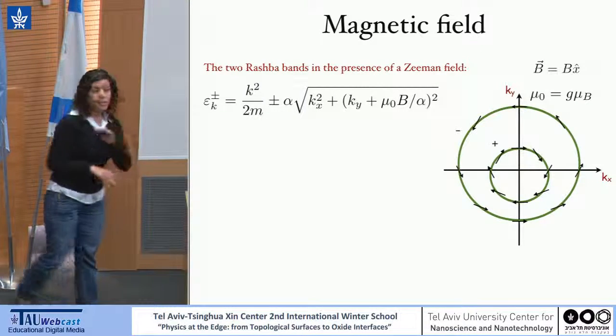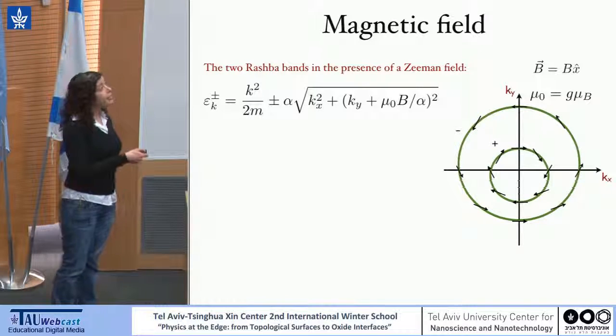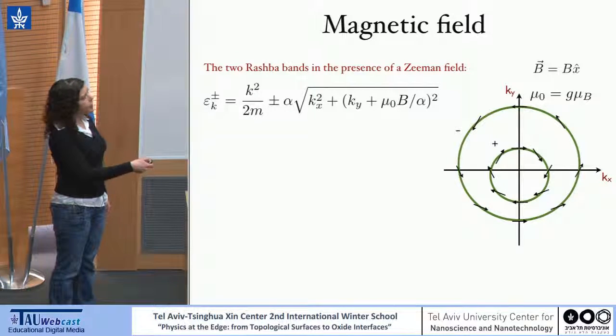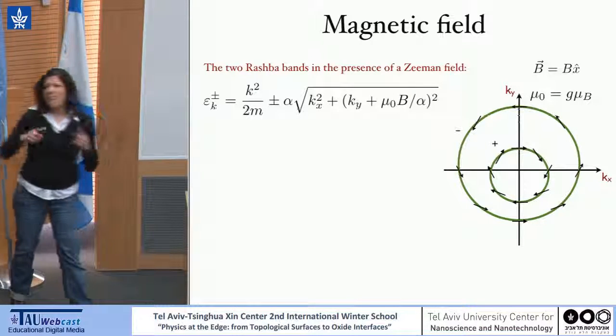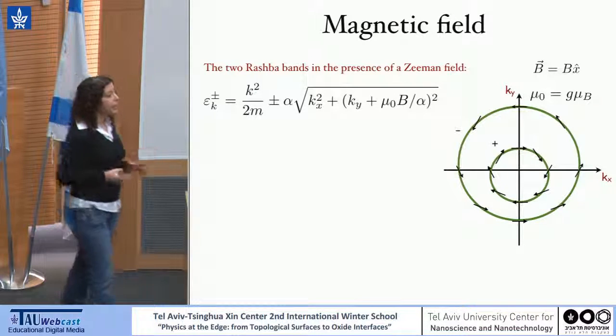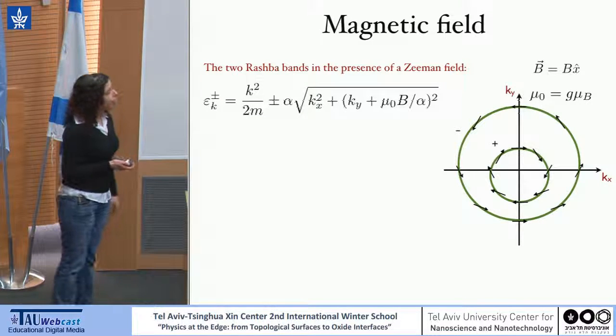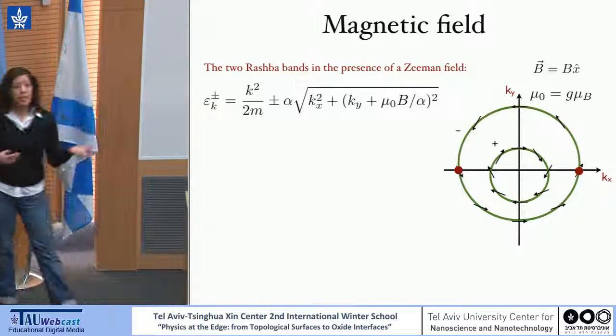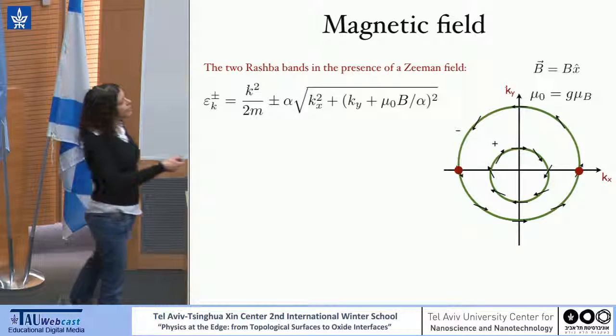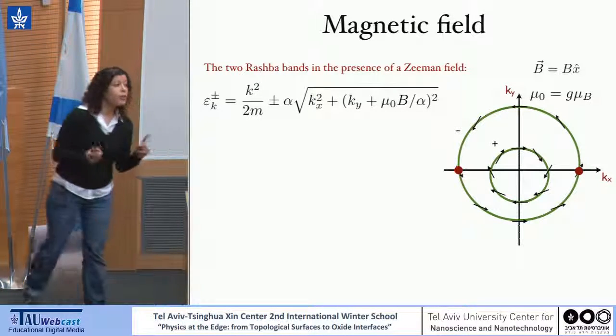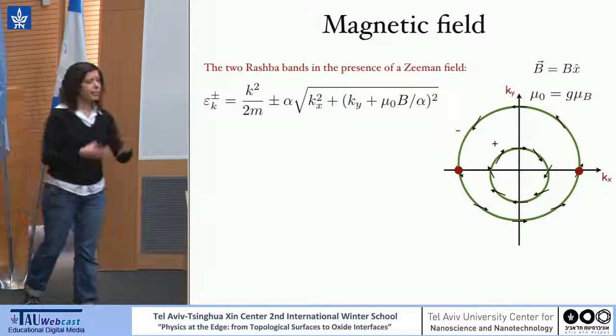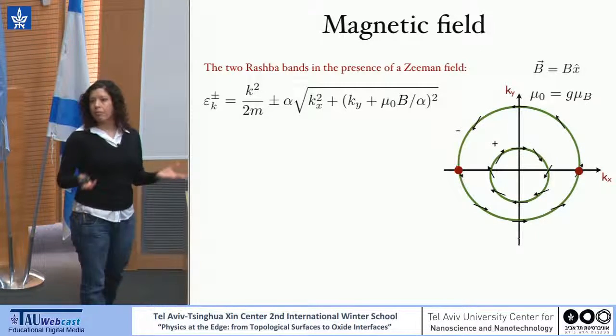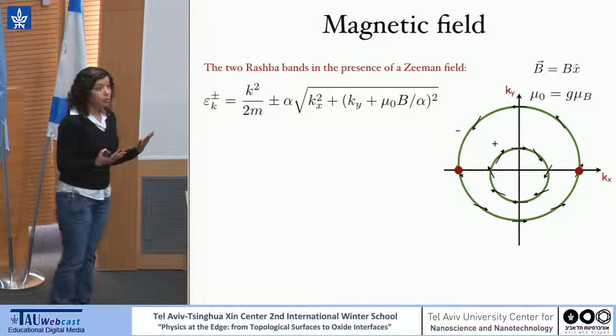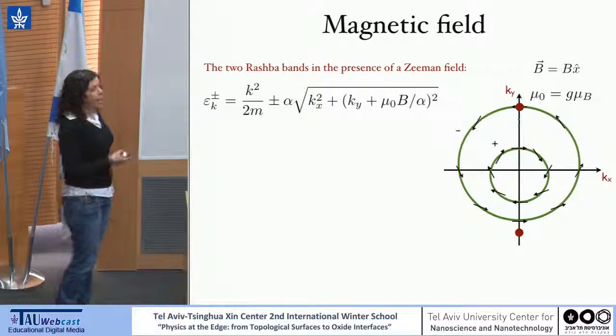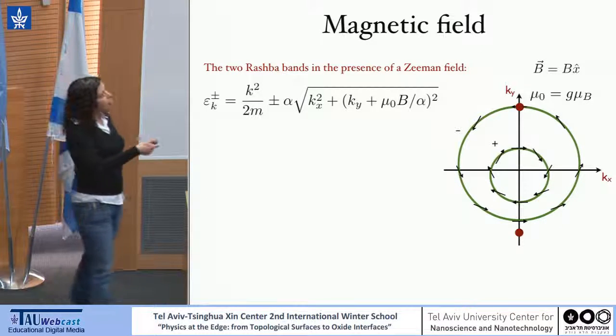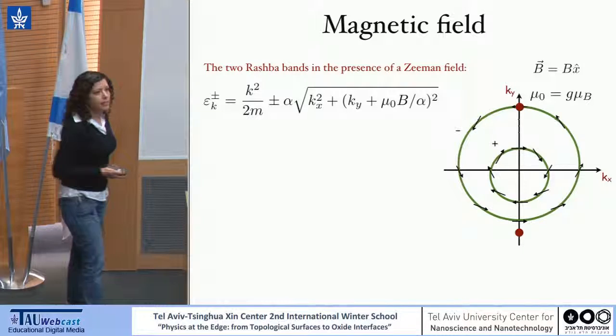Now let me add a magnetic field to the system. Parallel magnetic field, so Zeeman-like. The effect is basically to shift the Fermi surface. One Fermi surface goes up, the other one goes down, and now the spins are no longer perfectly aligned with the direction of the momentum. So now what happens if we are trying to pair electrons with momentum k and minus k? We can see that here, the spins are no longer antiparallel, as in a regular case when we have just a magnetic field in a superconductor. In the other direction, we can see that we cannot put both electrons on the Fermi surface.